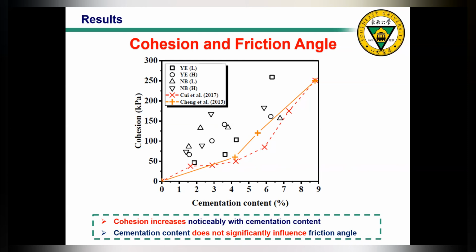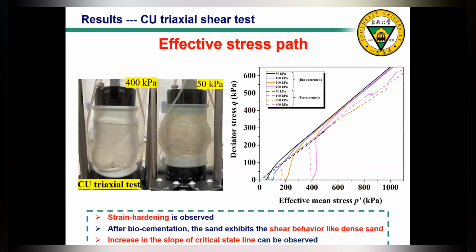So only cohesion is apparently affected. Okay, so next is the CU triaxial shear test. On the left-hand graph, that's the picture taken at the end of two CU triaxial shear tests. One is on the 400 kPa confining pressure, the other is on the 50 kPa. On the 400 kPa, the high level of confining pressure, we can see a clear shear band. However, for 50 kPa, it's like bulging.